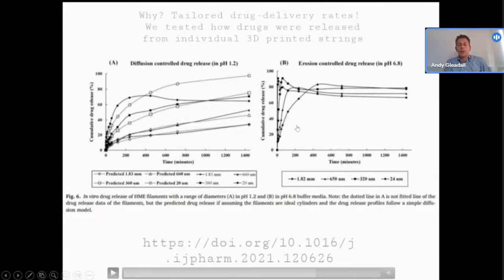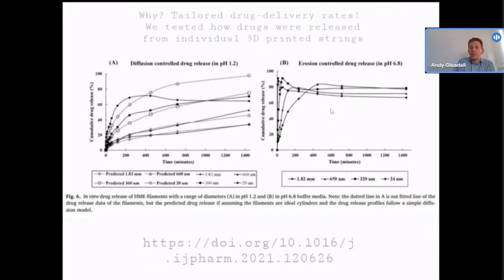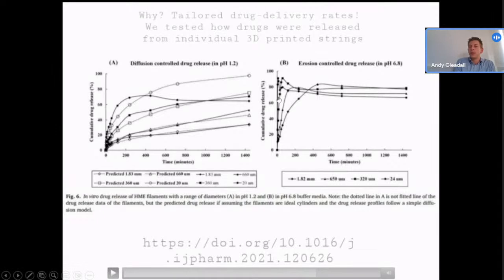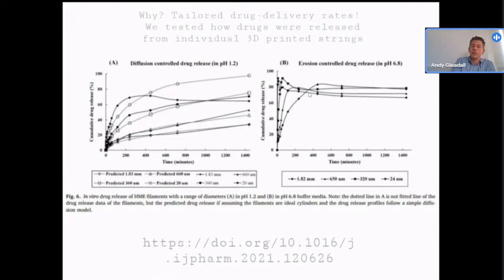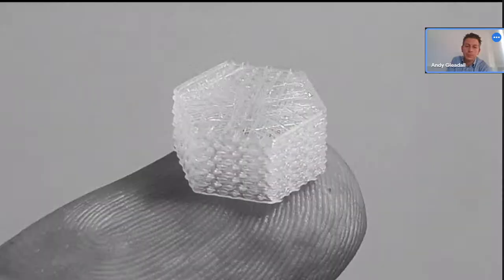So here we could print with the same material and the same printer, but get completely different performance just by tweaking what we're actually printing, which is great for drugs because we don't really want to have to print lots of different materials. If we can get lots of different treatments by printing the same material with the same process in slightly different ways, that's a real advantage.